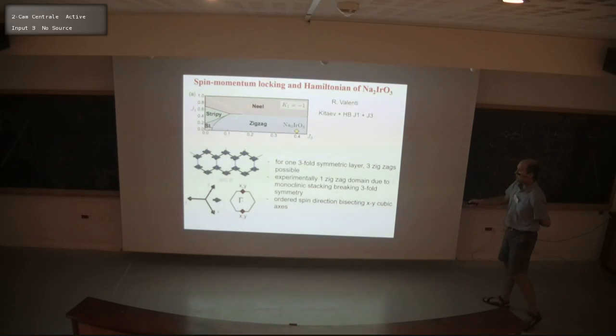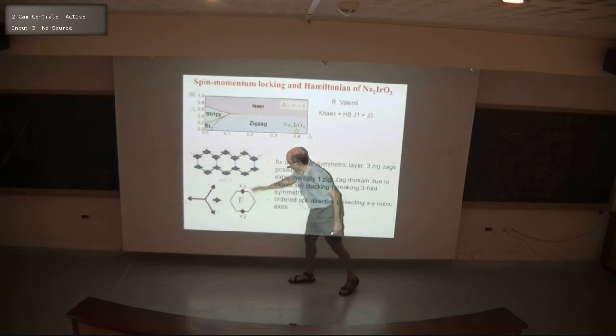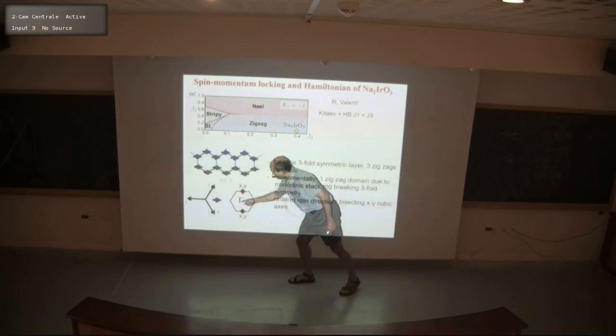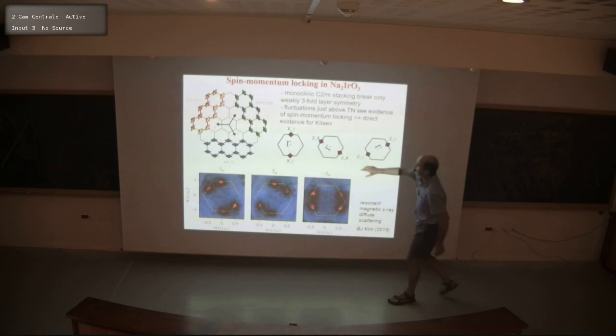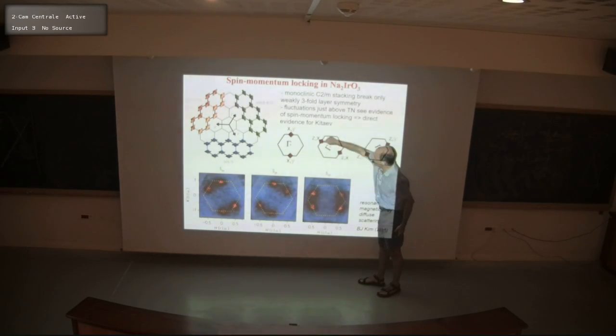And then it's possible also to find the moment orientation, and you see that for the zigzag that propagates vertically, the moments are bisecting the cubic axes x and y. Okay? So this Bragg peak here is expected to have polarization xy, and so this one. Now imagine the situation that we did have threefold symmetry, and then there will be another zigzag that's oriented this way, so there'll be Bragg peaks here, but they would have different polarization, Y and Z, and so on. So this would be the position with Bragg peaks with these polarizations if we propagated in this zigzag, and the last figure would be if we had this other zigzag.